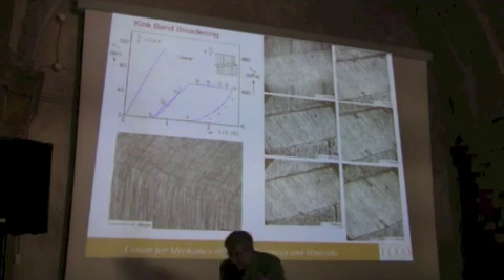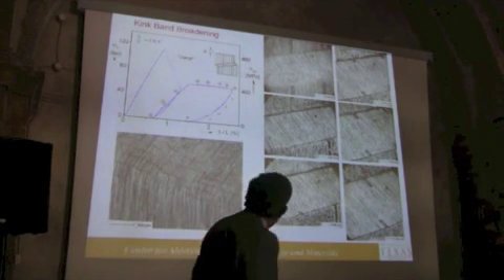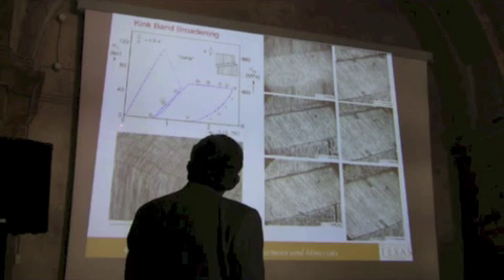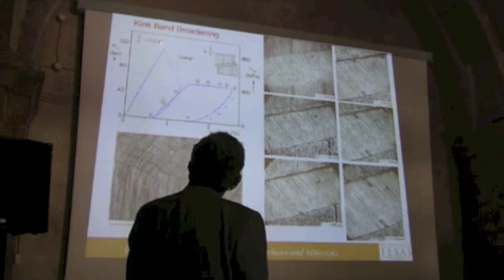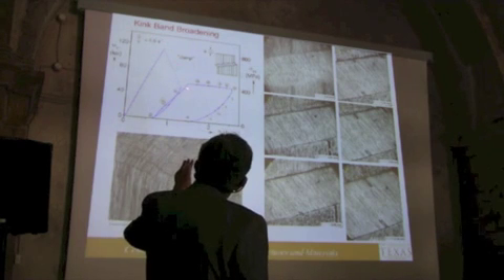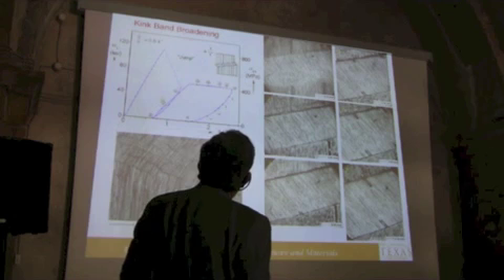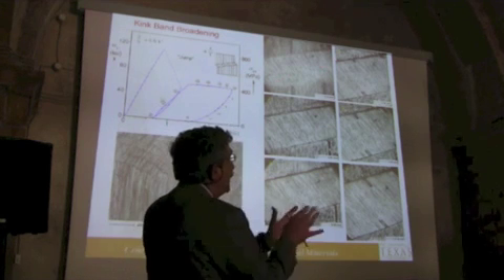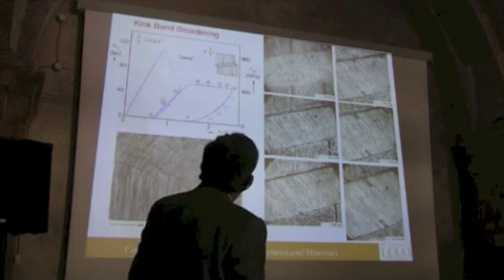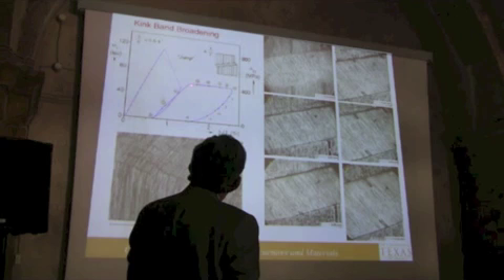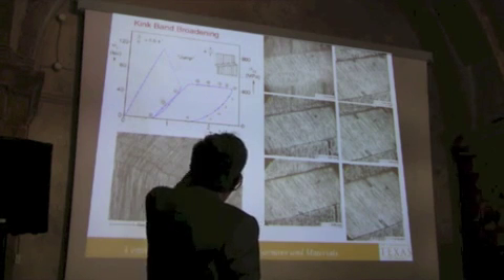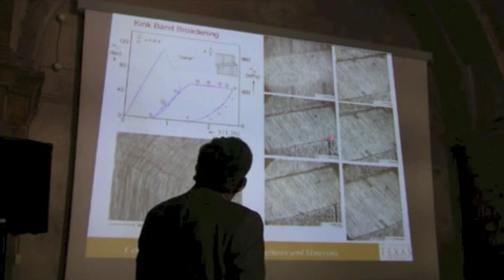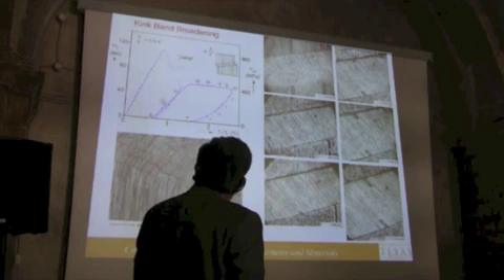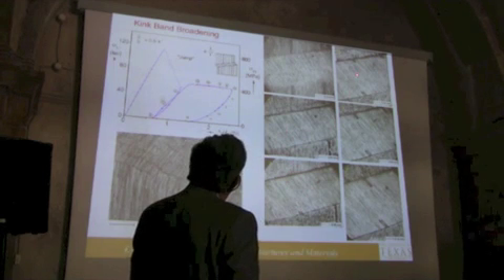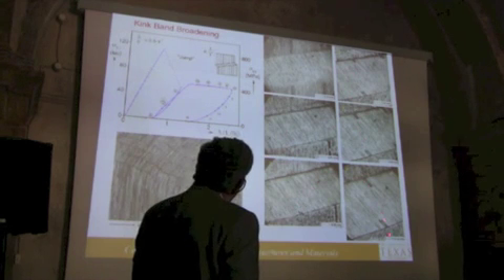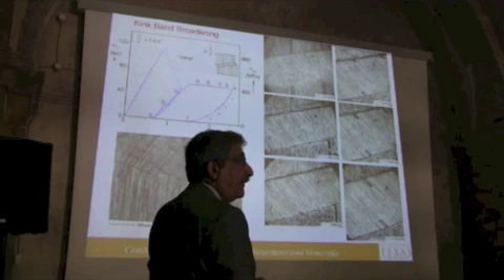So let me, I'll show you this, maybe a movie. So, this is an experiment in which we loaded it, and then it failed, and this jump is due to the failure, and let us say that we have ended up with this kink band. It's protected on either side, that's why it has survived. Now, if you continue compressing it, okay, in this case we unloaded and reloaded, you see that the band sharpens, and I hope you can see that it is widening, it's broadening and broadening, and while that is going on, this is a flat plateau.